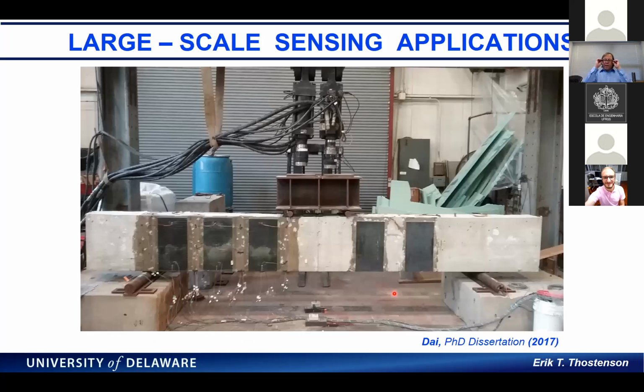So I won't talk too much about this, but this is one of the test specimens. The span is, I believe, over 3 meters. The specimen itself is about 4 meters long. And one thing you see on the left-hand side, these are U-wraps or shear wraps that have fiber reinforcement with them that's intended to be a repair because this beam was pre-cracked, and this does not have enough shear reinforcement. So this was to repair, but also detect damage. And then over here, these are the sensor only. This is some work by my PhD student, Hongbo Dai.